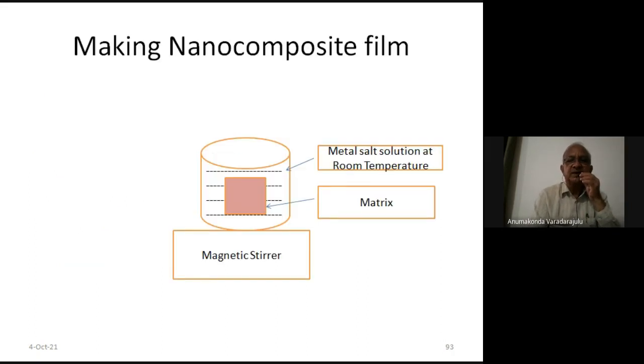So this is the process. We are taking the metal salt solution here, and then introduced this matrix wet film, and then on a magnetic stirrer at room temperature. The entire process is done at room temperature here, and after 24 hours, take it out and then dry it. We'll be getting the dry film.